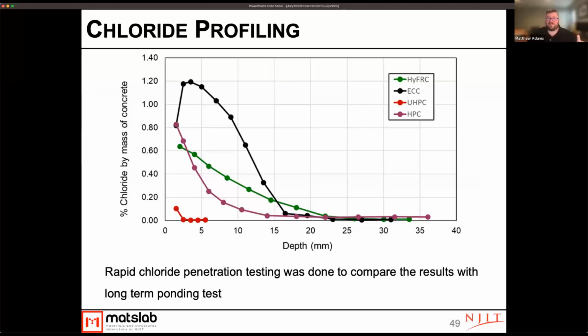We see with the UHPC system, of course, those chlorides got basically nowhere. There was a little bit on the surface, but once you get about 2 or 3 millimeters deep, we had no chlorides. The ECC system had a much higher chloride rate early on, but it quickly dives off. Our rebar was at 25 millimeters. So really only the high FRC was close to having measurable chlorides at that level.